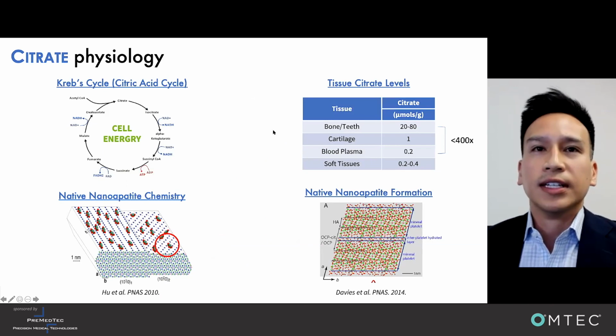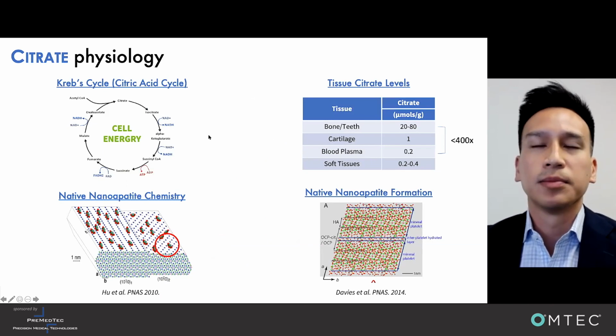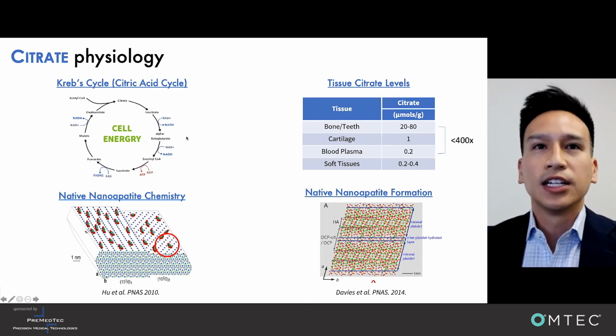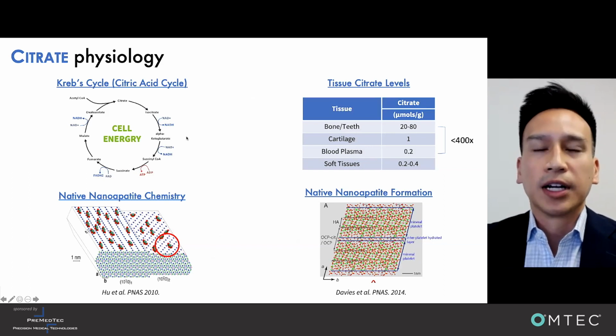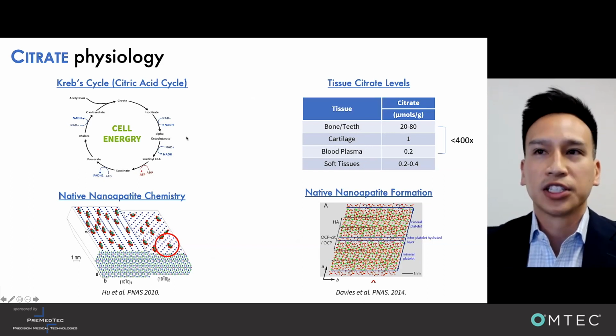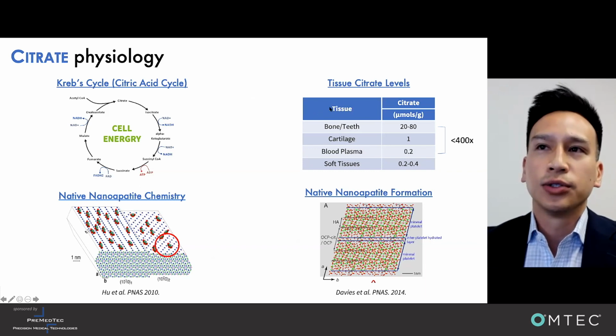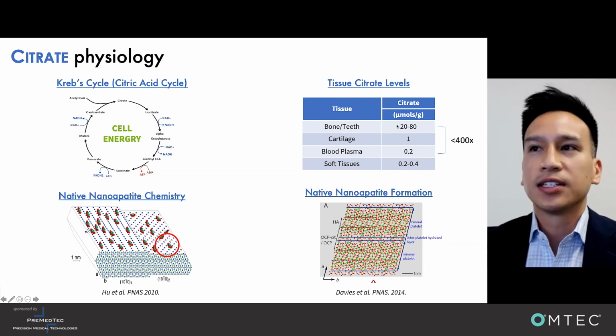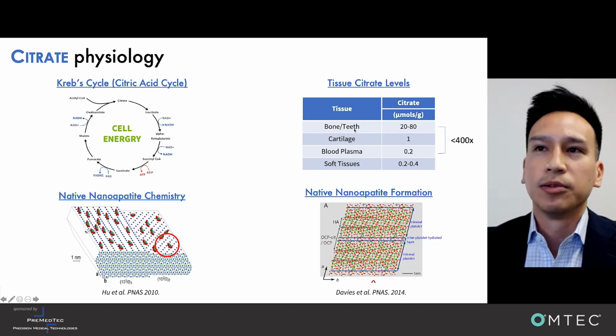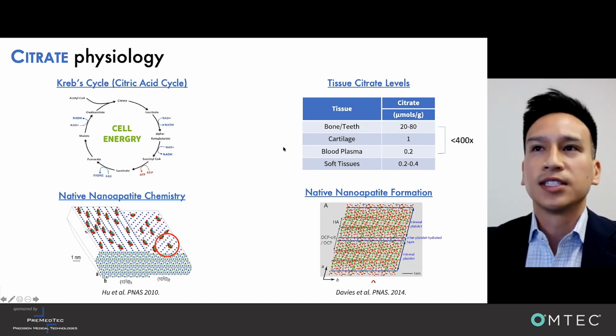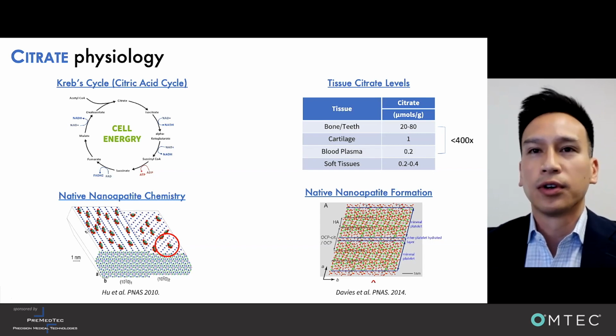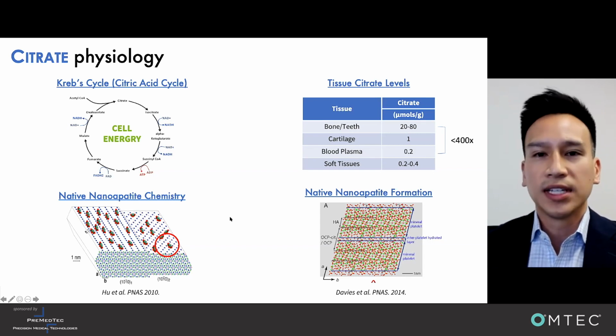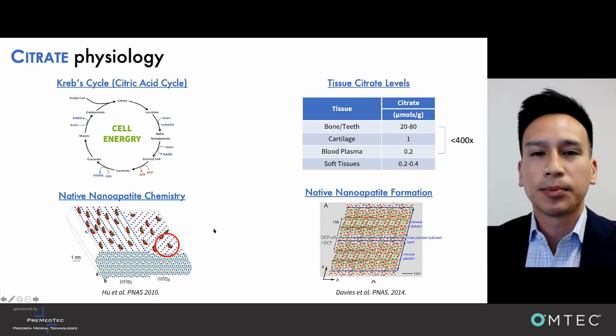Citrate also, in addition to biomaterial design, offers many biologic benefits. It's traditionally known to be a key contributor to the Krebs cycle for energy production. But when you look at the tissue citrate levels, you can see that there's almost 400 times more citrate in bone and teeth than soft tissues and blood plasma. Researchers have known that citrate levels were high in bone for a while, but it wasn't until 2010 and 2014 in 2 separate articles published in PNAS where they elucidated the role of citrate in bone physiology.